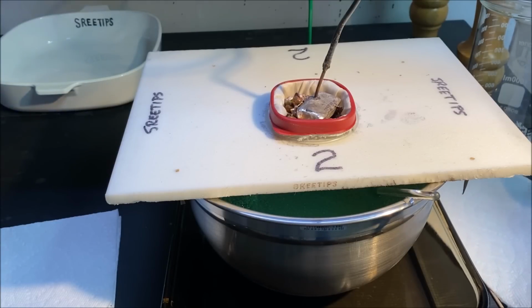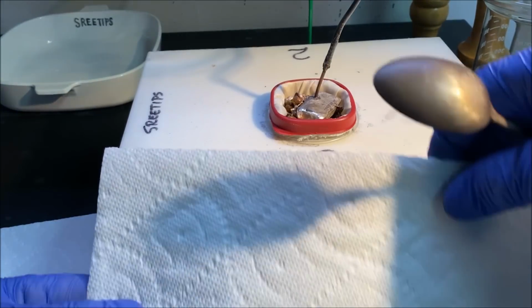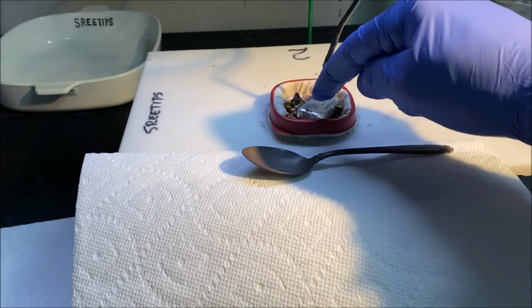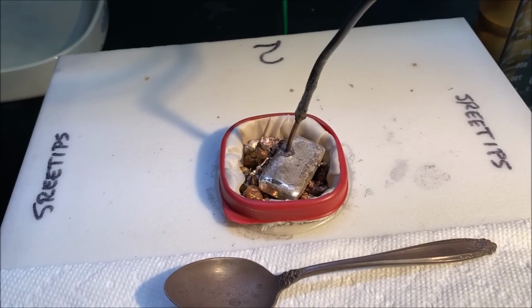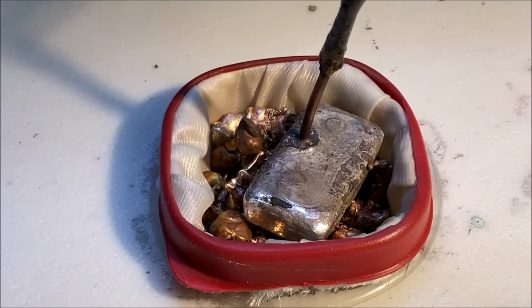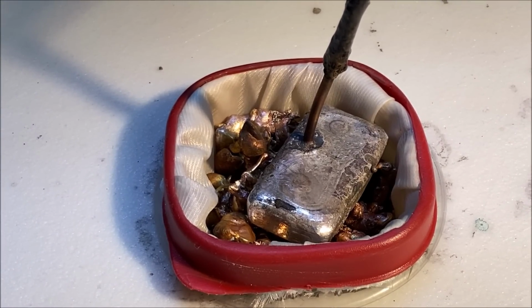What we're doing is running the impure silver through this cell, and this is going to have impurities in it, including copper and possibly some platinum group metals. And those impurities, the copper will dissolve and go through the filter and get down into the electrolyte, but anything like gold or platinum group metals will remain trapped in that filter, and then we can process those filters and recover those precious metals.